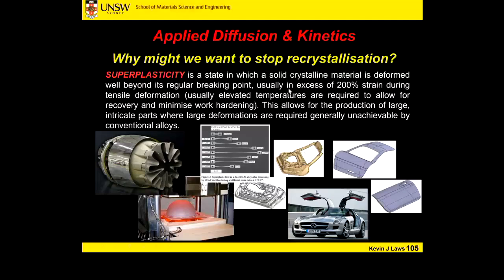It's usually done at elevated temperatures, required to allow recovery and minimise work hardening. So we're kind of minimising the effect of dislocations and things on work hardening, and we're just keeping these grains all the same size. The deformation mechanism is the actual grains sliding around one another.